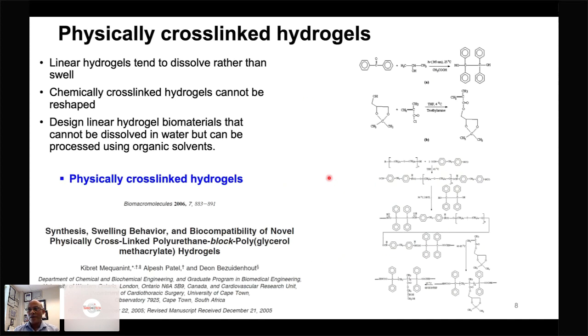So one of the earliest physically cross-linked hydrogels that we have designed with biomedical application in mind was published in Biomacromolecules, you can see in 2006. And then with this publication, we expanded the idea that physically cross-linked hydrogels can be synthesized quite successfully. So as you all know, linear hydrogels tend to dissolve rather than swell. So if you synthesize a hydrogel forming material, and if it's a linear polymer, then it dissolves in water, but then you are not getting a hydrogel material. So that's pretty much useless.